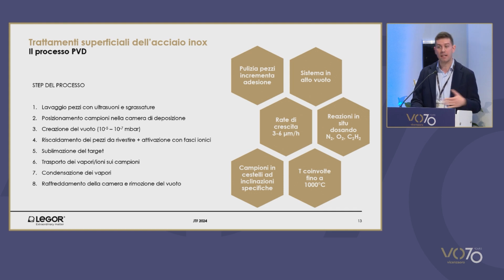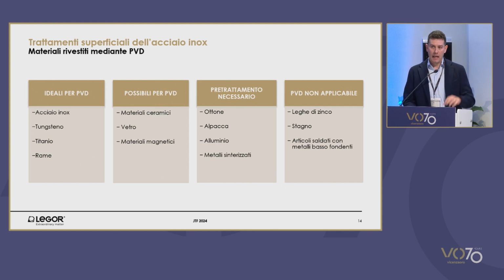included in the target. The temperature ranges between 100 and 1000 degrees, depending on the type of target and the type of process required. And 3-6 microns per hour are then added on the substrate. This technology can only be used for certain materials, those that are extremely strong, such as tungsten, copper, and stainless steel.